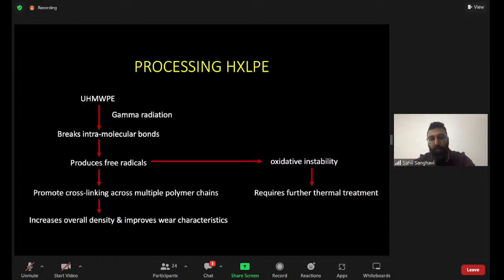So just a brief note on the processing of highly cross-linked polyethylene. Basically the conventional poly or ultra-high molecular weight polyethylene would undergo gamma radiation. This would in turn break the intramolecular bonds and produce free radicals. The free radicals produced would promote cross-linking across multiple polymer chains and thereby increase the overall density and wear characteristics of the polyethylene. However, the free radicals produced would also cause some oxidative instability, and this required further thermal treatment.